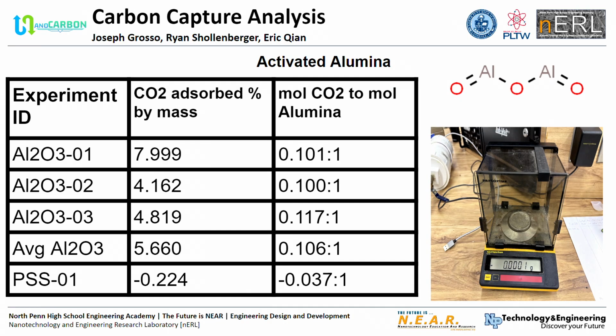This data shows the CO2 percentage absorbed based off of our material's mass. Multiple experiments were run, and the average percentage absorbed was about 5.7%. PSS, on the other hand, not only did not absorb CO2, but also lost mass throughout the experiment.